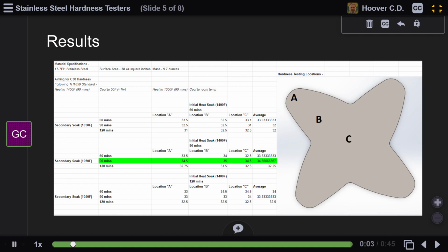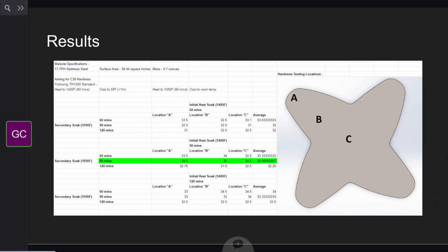As shown in the table here, an initial soak of 90 minutes at 1400 degrees Fahrenheit with a secondary soak of 90 minutes at 1050 degrees Fahrenheit yielded the best results. This is in line with industry standard. However, we did not quite hit the industry standard hardness of C38 Rockwell. This could be due to a variety of factors, such as not scuffing the test sample enough when we were testing, or leaving it out too long and it didn't quite get to 55 degrees. Could be anything like that.